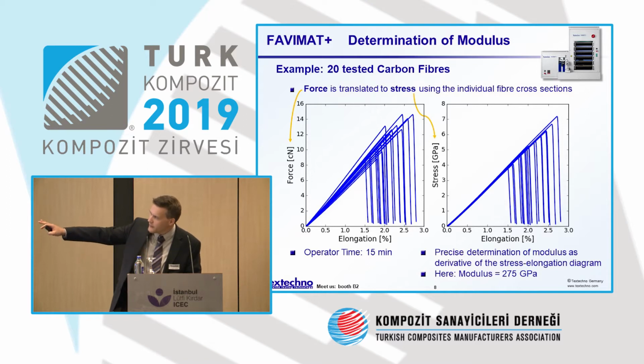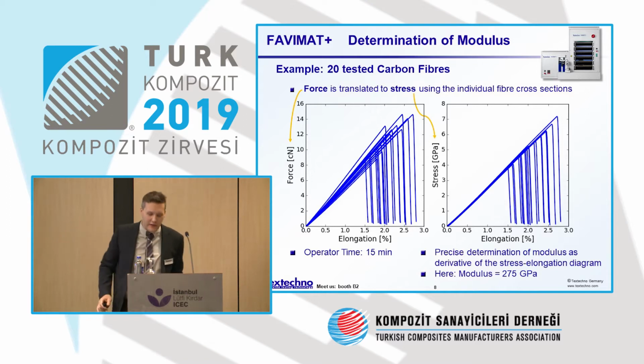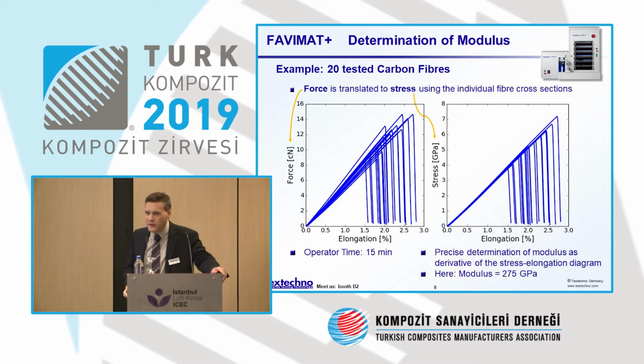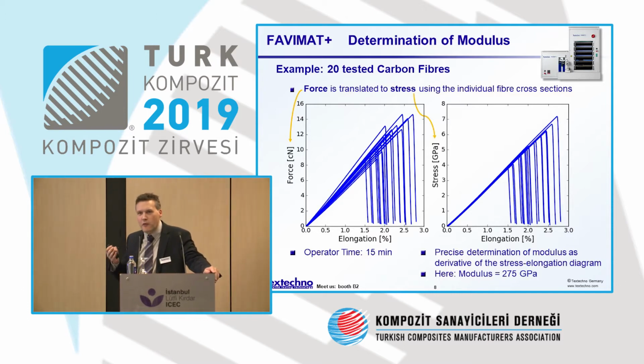So I've brought with me an example here of 20 carbon fibers that have been tested. It takes about 15 minutes to do the test, and it tells you the modulus of the fiber as well as the ultimate breaking strength in 15 minutes. You see what the FAVIMAT has recorded here on the left-hand side is a force elongation curve, and you see for these 20 fibers the individual force elongation diagrams.